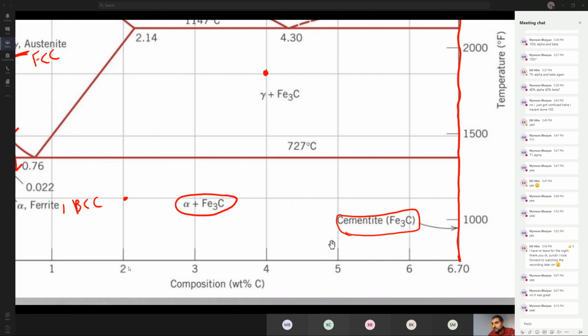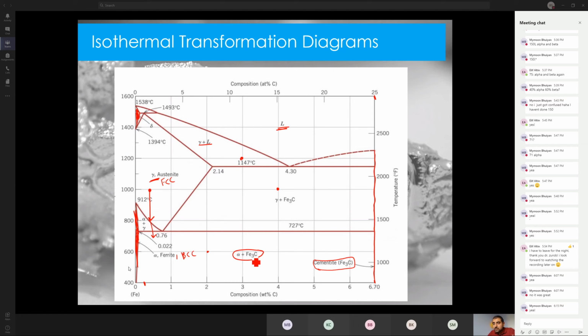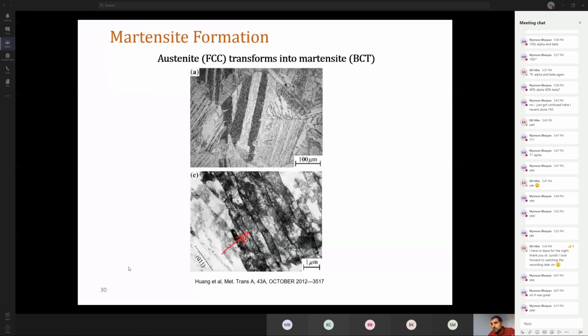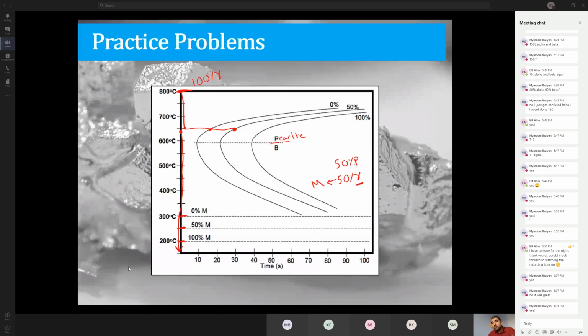So what is alpha and Fe3C? Alpha and Fe3C is essentially our pearlite. We said pearlite is alpha plus Fe3C. So is the pearlite okay to be present at room temperature? Absolutely. It's an equilibrium phase. That's what the phase diagram has, so it should be there. And therefore, it should stay there. Once you make the equilibrium phase, the one that shows up on the phase diagram, it stays there forever. It's supposed to be there. So nothing happens to our pearlite. The only thing that changed is our gamma or our austenite. It goes to martensite. So the final outcome is 50% pearlite and 50% martensite.